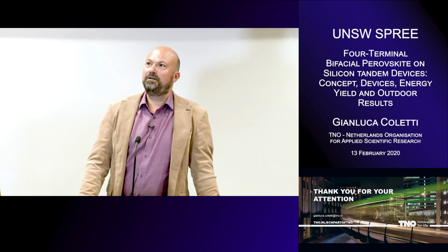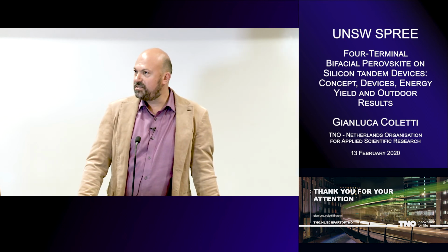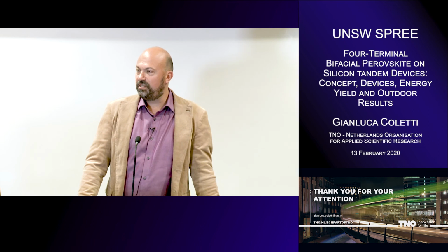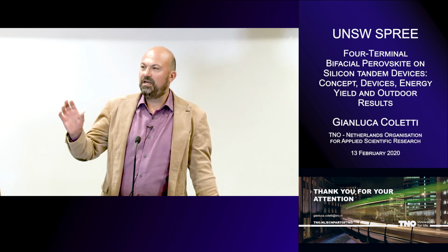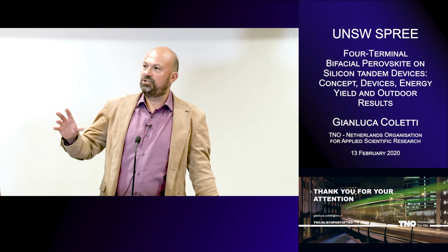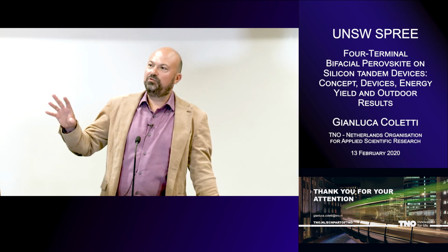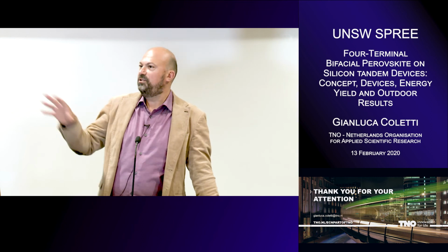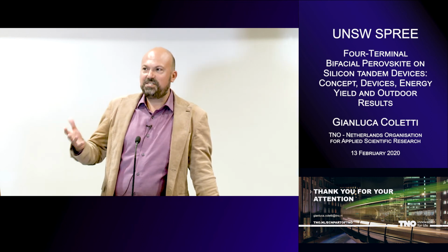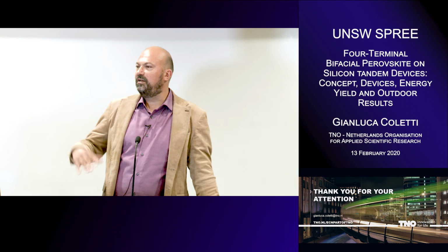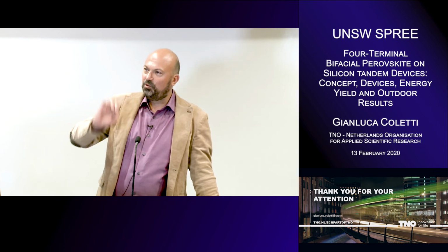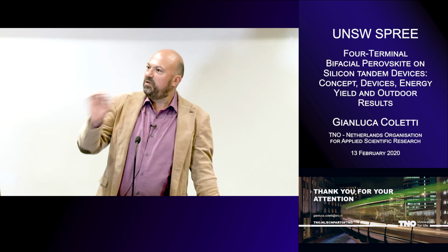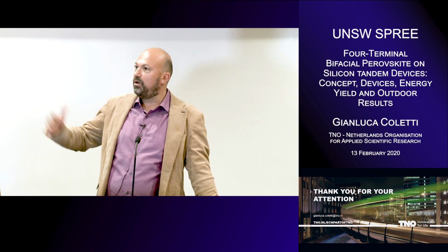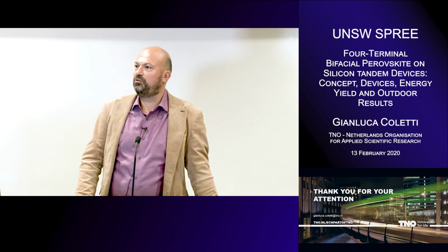Yeah, it makes a difference, and the surface makes a difference. You can find literature data that show that the shift is not a huge shift, so much that in most conditions you are below the error that you have anyhow in the measurement, but this is something really important. So in a follow-up publication we are including this effect, which can be marginal, but when you calculate the energy yield, it can start to become important.